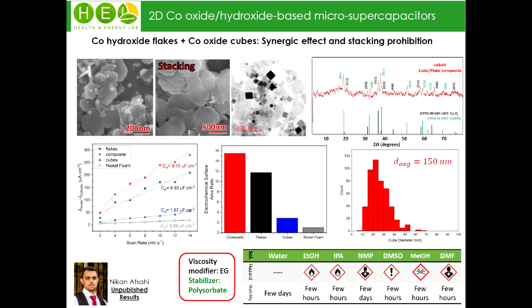In another work, we tried to inkjet print devices based on cobalt hydroxide flakes, and to avoid the restacking of such flakes, we employed cobalt oxide nanocubes inside the system.